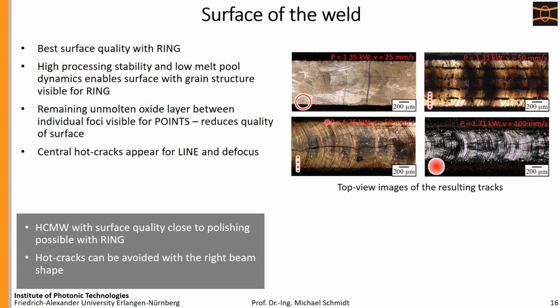So the shape of the solidification area, to be more precise, is strongly connected to the growth of, for example, dendrites. And this again is connected to whether you have hot cracking or not. So here we have a first indicator that with the different shapes, as we expected, you are able not only to have less spatter, but also to influence hot cracking behavior, which is quite good, by the way.